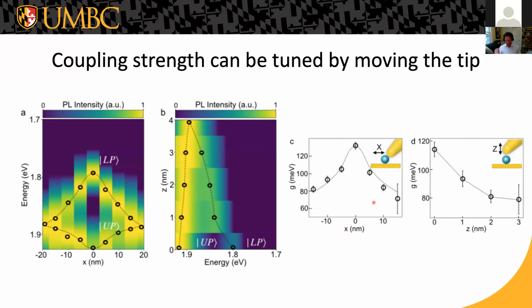And we can also move the tip relative to one quantum dot. So we can change the coupling strength by scanning the tip either laterally or vertically, bringing it from further away from the quantum dot on the sample to right on top of the quantum dot, and seeing this single peak split into two and then go back down to one. And as the tip is moved up vertically, the split peak merges into one peak. So the coupling strength dies off on just a couple of nanometer scale in the vertical direction, whereas in the horizontal direction, you can scan the tip over about 10 nanometers before you start to lose this strong coupling.